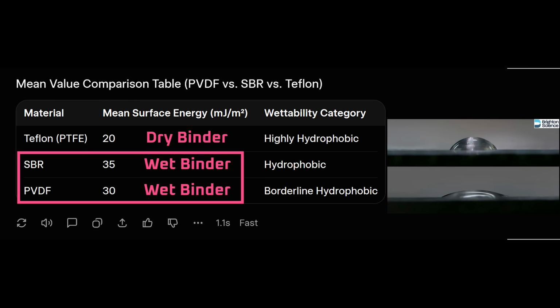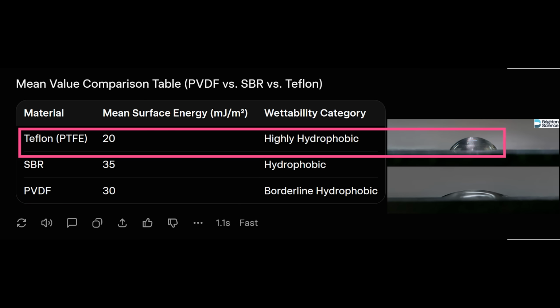Before we move on, interestingly, the plasma treatment process could also be very useful in a wet electrode coating process. But Tesla discovered the plasma treatment process first as a matter of necessity. That's because the surface energy of the PTFE, or Teflon, that's used in the dry electrode coating process is even lower than the binders used in a wet coating process, meaning it's more resistant to electrolyte saturation and was likely causing Tesla headaches for manufacturing throughput.